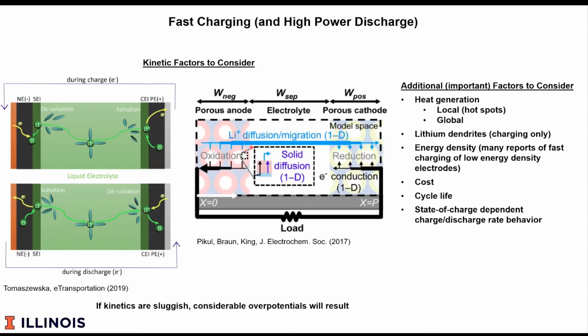During discharging, the primary concern is local heating, which then accelerates the transport in that region, which leads to additional heating and feedback that often then leads to failure over time. So what are the factors along with dendrite or some of the kinetic factors? I already mentioned heat generation. That can be both local and global. Lithium dendrites, charging only. You have to pay very close attention to energy density.